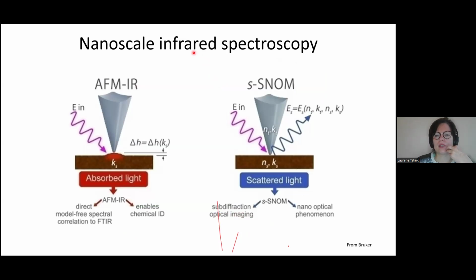So the way nanoscale infrared works is that it uses the AFM platform and then it combines the platform with infrared illumination. So we shine a laser that emits in the infrared range on the sample right below the tip. So there are different modes that have been developed, and today I'm going to talk about this mode here, where the laser comes from the top side, and as the material absorbs the light, it's going to heat a little bit and expand, and the cantilever that is sitting is going to deflect, like we talked about earlier. And so by recording this deflection as a function of what we're doing with the laser, we're able to get to the chemical information.